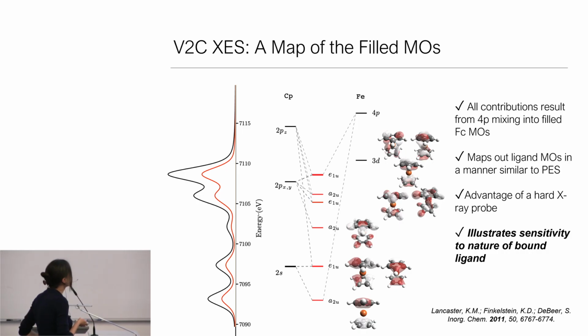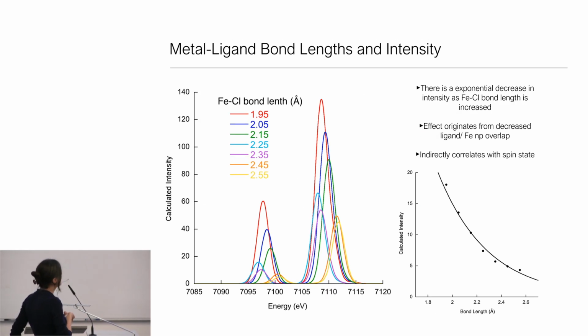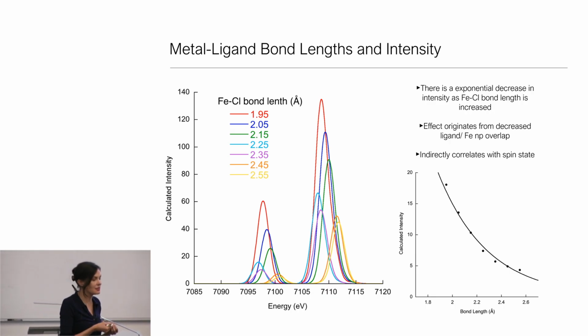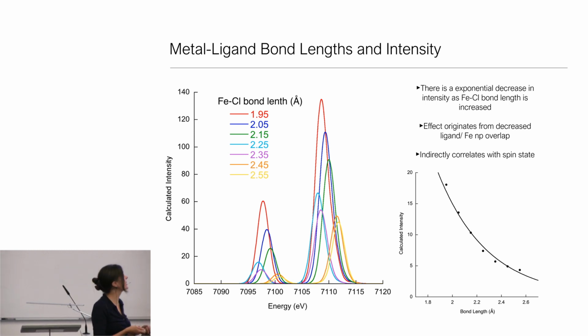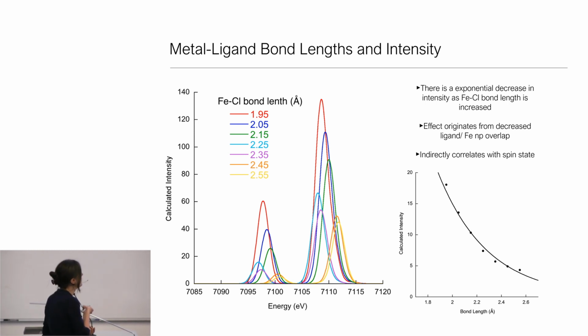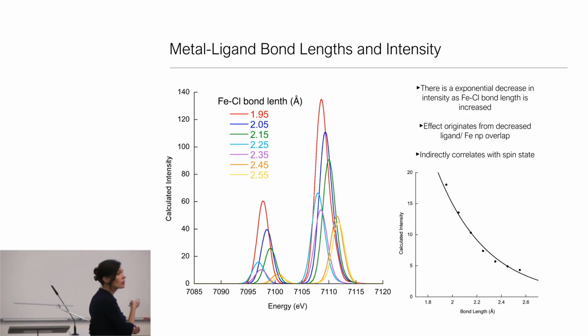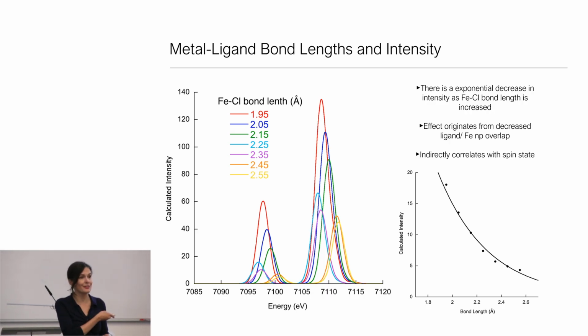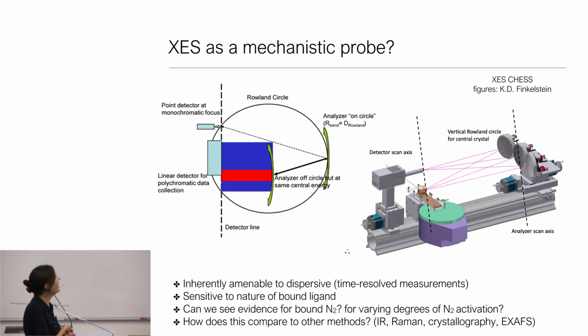I do want to bring up that these intensities are based on metal ligand bond distances. So I showed you that the low spin complexes were actually quite a bit more intense. And that intensity basically comes from the fact that the shorter the metal ligand bond distance is, the more p mixing you can actually get. And so there's basically an exponential dependence on the distance. I don't have the reference here, but this was an early 2010 JACS paper, where the first author was one of my first undergrads. So she was awesome.